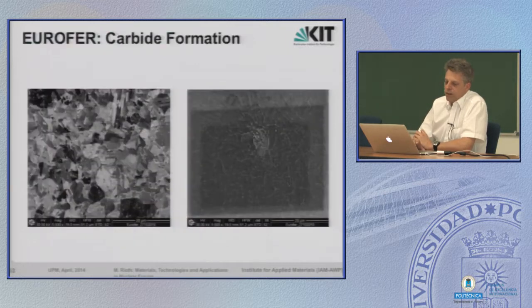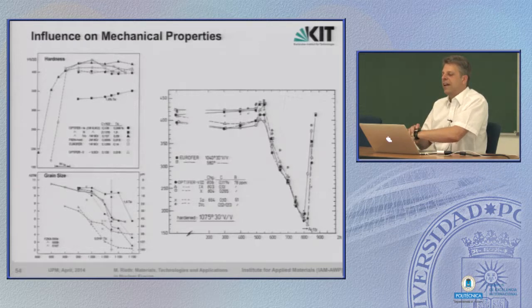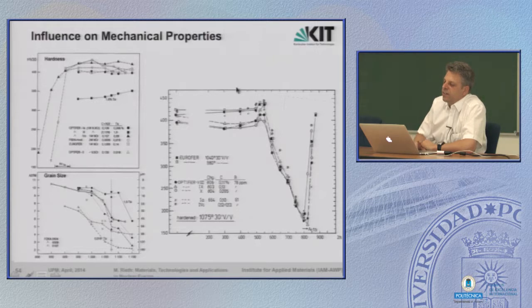Finally, here again, this is a visualization of where the carbon ends. You see it here along the grain or lath structure, the white dots that happen during tempering. And finally, the influence on the mechanical properties. You can easily see this in the hardness curves. Let's first start with heating the material up. It starts from 800 to 1150. See, it's a bit small, but if you perform this annealing and cool down, then you produce martensite with this captured carbon. It's called untempered martensite, which has a very high hardness, above 400 in Vickers hardness.